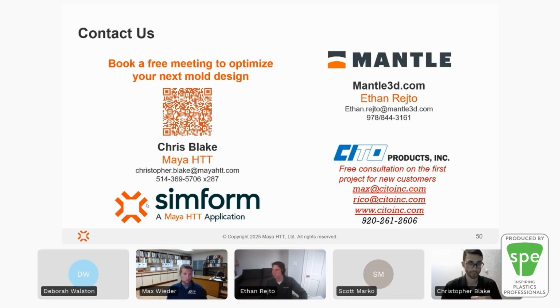Okay, next question. What is the difference between the hybrid manufacturing method proposed and powder bed fusion technology? Yeah, so powder bed fusion technology is using a powder instead of a paste as we are, and they're directly producing metal components by melting or sintering the metal powder with a laser, applying a lot of energy to that powder to do the sintering at that laser point. Our technology is quite different in that we're printing the metal powder as a paste. So the powder is completely loose in this stage, but it's bound in a binder to create the part. Then it goes into a sintering where we're doing all of the thermal processing at once instead of selectively doing it. That also means we can very uniformly heat and cool the part during that process.